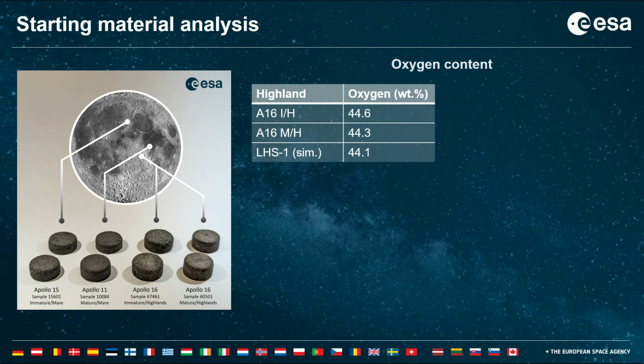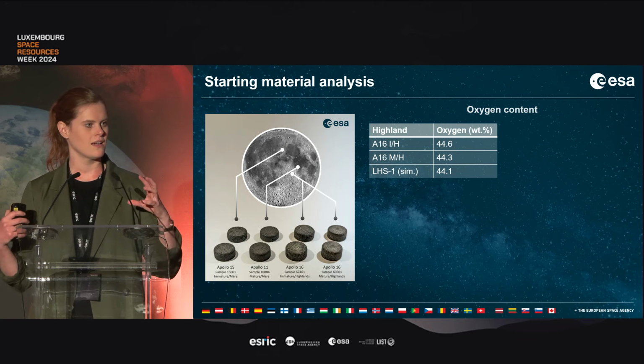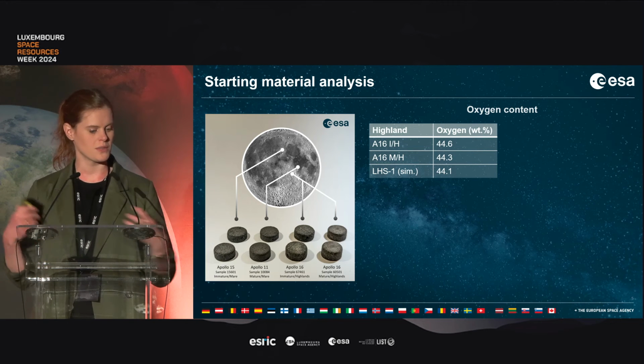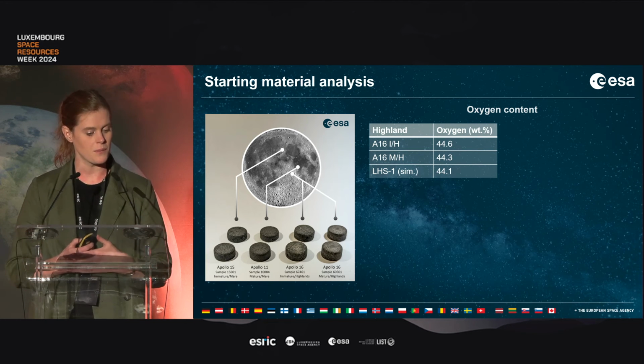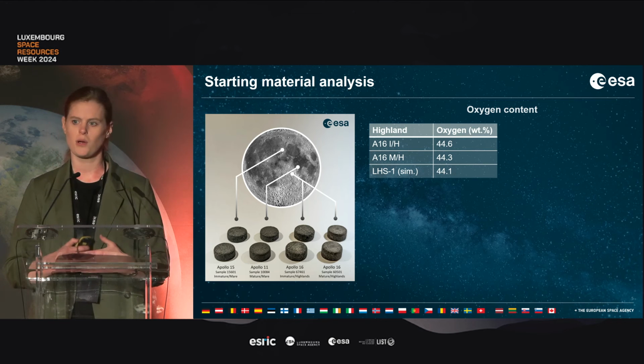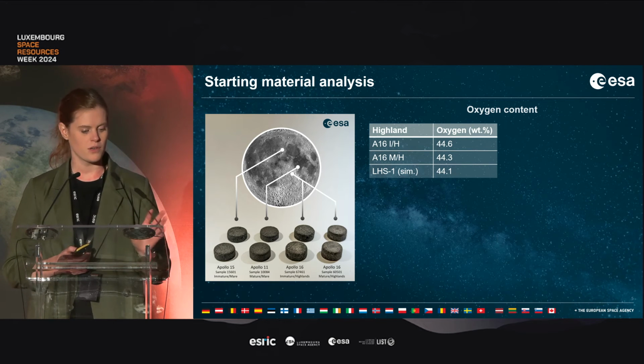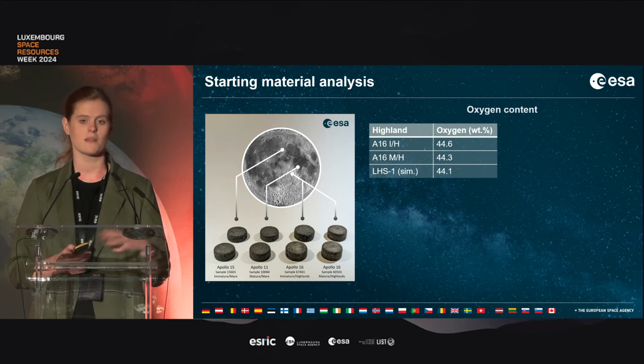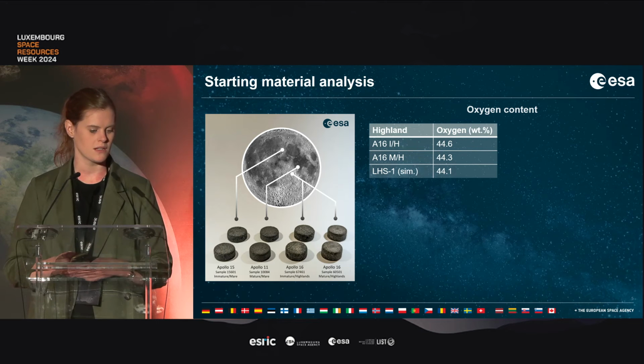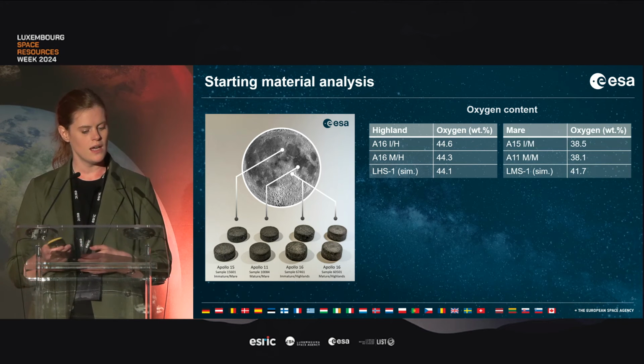So the first thing we wanted to do was measure the oxygen content. Of course, if we want to understand how the oxygen extraction processes worked, we need to know how much oxygen we have to begin with. So the Highland material, the Apollo 16 material, had roughly 44% weight oxygen, and this was very similar to the Highland simulant material, also around 44%.